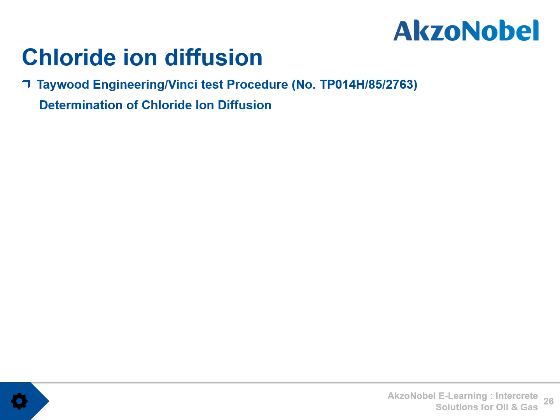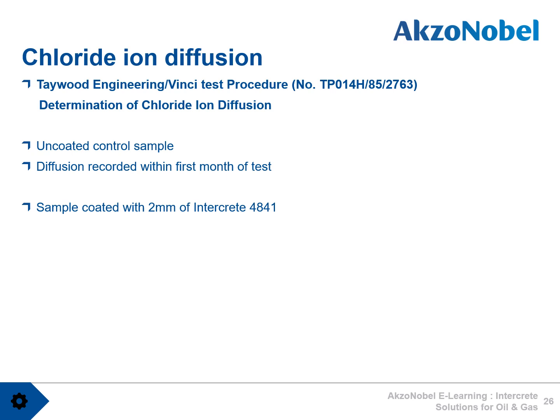Taywood Labs, now Vinci Technology Centre, have been testing our cementitious coating Intercrete 4841 to determine chloride ion diffusion, the ability for chlorides to travel through the coating. The system has been on real-time test continually since the 1980s. And 30 years on, the old uncoated sample showed diffusion within the first month of test. 30 years on, Intercrete 4841, no steady state of flux recorded after 30 years on test.